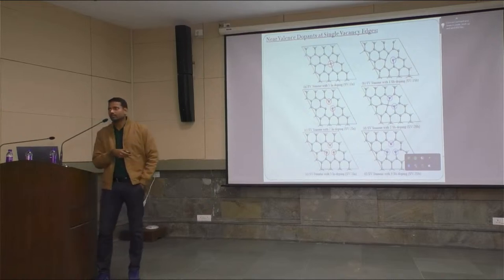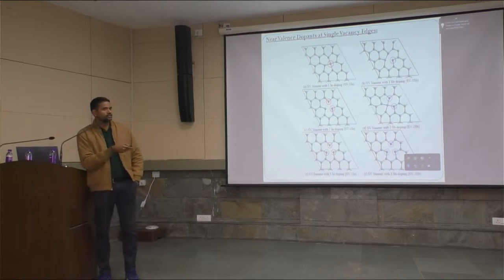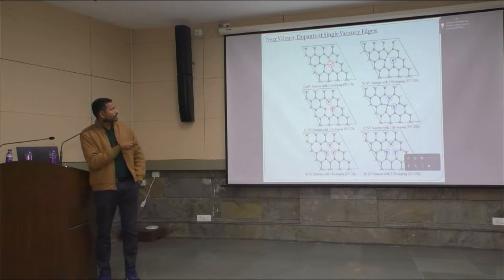To study the different mechanisms further, we have introduced these near valence dopants, indium and antimony, at the single vacancy edges. Initially, one indium is positioned at the single vacancy edge. Thereafter, two indium atom dopants are positioned at the edges. Thereafter, three indium atoms are positioned at the edges. And similarly, the antimony dopants are also positioned at the edges.